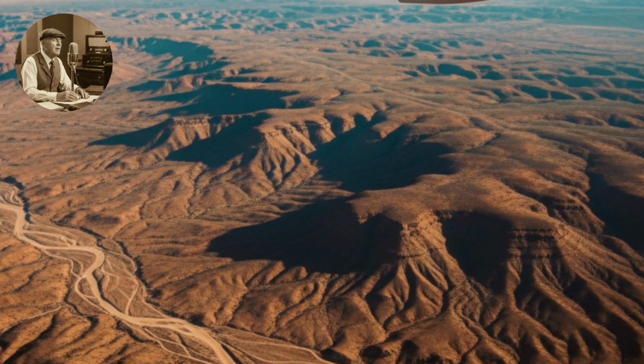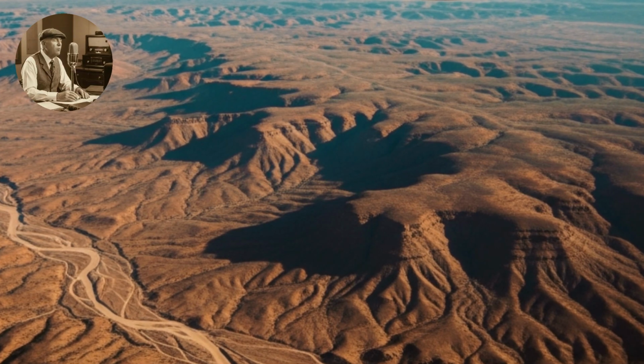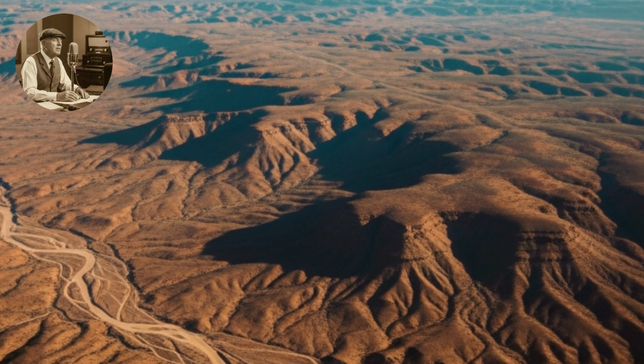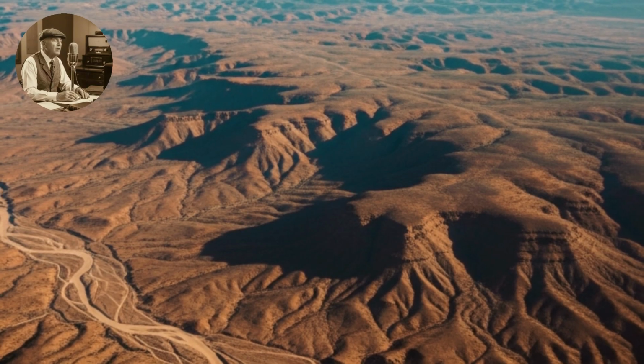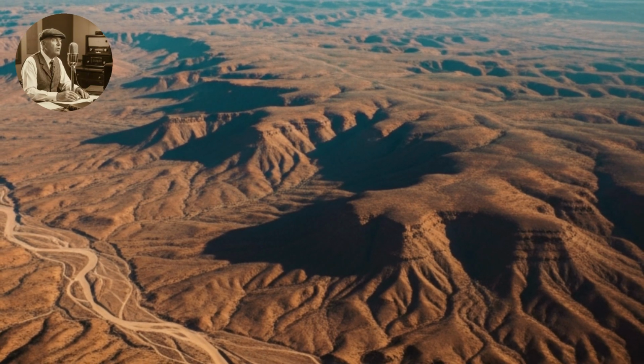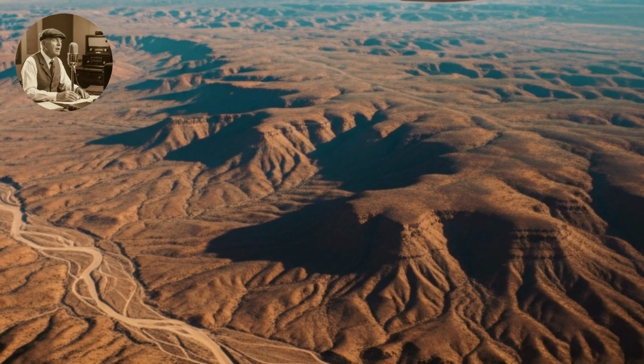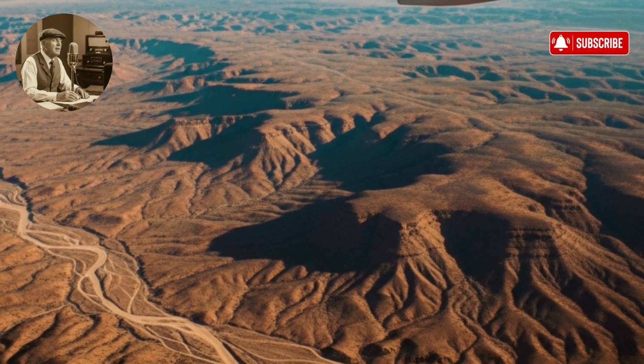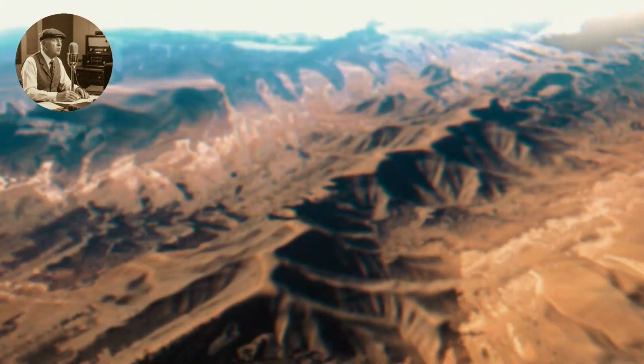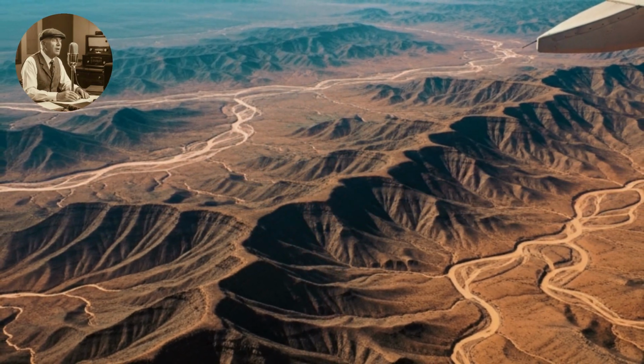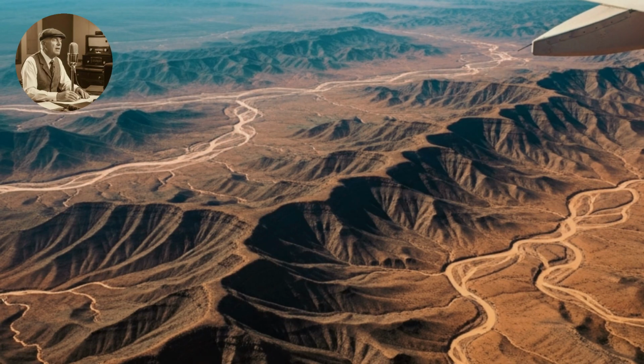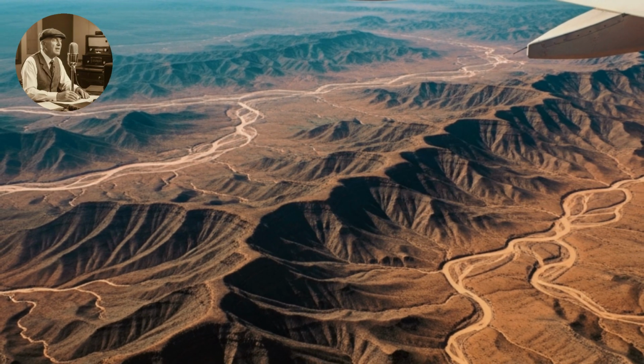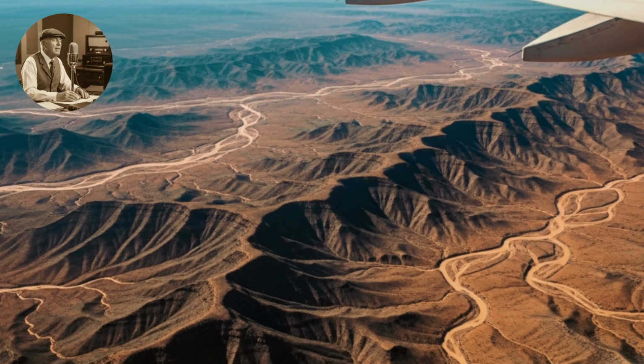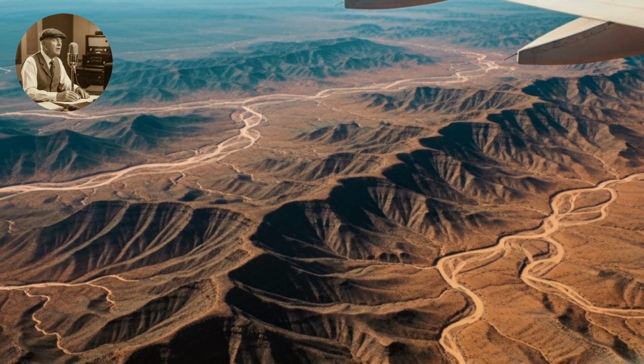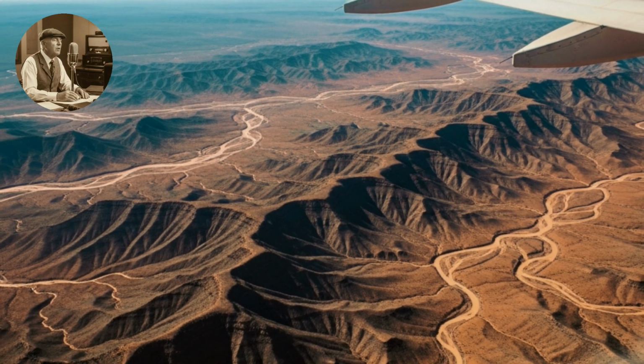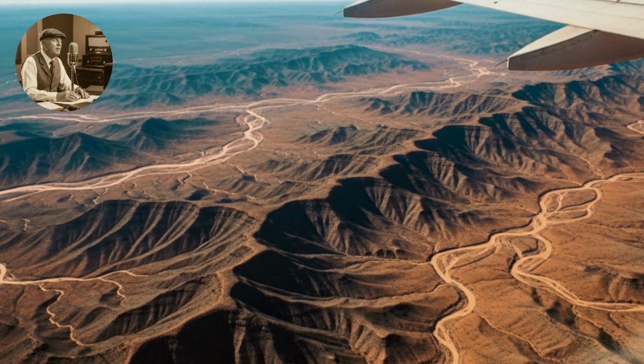At the center of the accident was a structural issue invisible to pilots and passengers alike. Inside the wing of the aircraft, the main spar contained several bolt holes used to connect structural components together. These holes were reinforced to ensure that stress remained within safe limits during flight. However, bolt holes also represent natural points where stress can concentrate. Under repeated loading cycles, such as those experienced during thousands of flights, tiny cracks can begin forming at these locations. Normally, such cracks grow slowly.